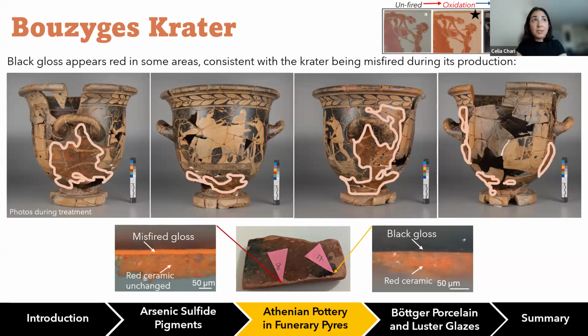This usually happens when in the kiln there's an uneven distribution of heat. Perhaps it's because of the placement, perhaps it's because of the actual firing that took place. Prolonged heating times could cause this too. So there are many different factors that could result in misfiring.